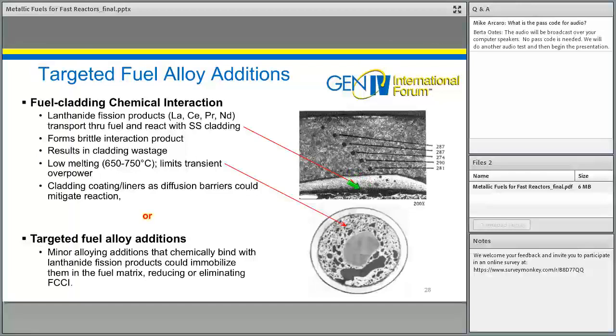And they produce this brittle interaction layer that can't support any load. And so as this reaction continues, you're basically reducing the load-bearing capability of your cladding. But even worse than that, the composition of this reaction product is very much eutectic-like. It's like a eutectic between rare earth elements and iron, and it melts at a relatively low temperature.